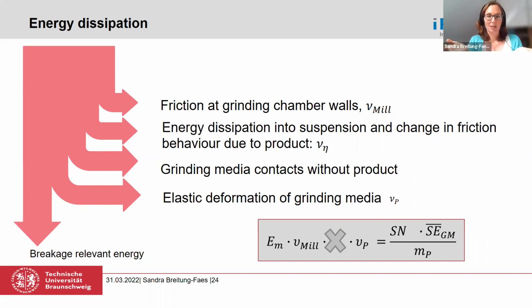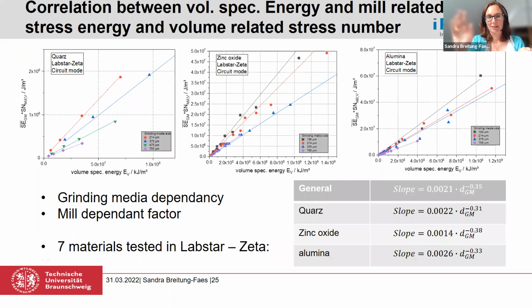So I thought, okay, when I need to run experiments without material and with material, it's far too complicated. I said, okay, I run experiments with the material and different grinding media sizes, and then you can come up with these curves here, where you have on the y-axis the product of the mean stress energy of the grinding media and the stress number of the mill in relation to a volume-specific energy. The volume-specific energy is in principle the same definition as the mass-specific energy, only that I related it to the volume of the product and not the mass.